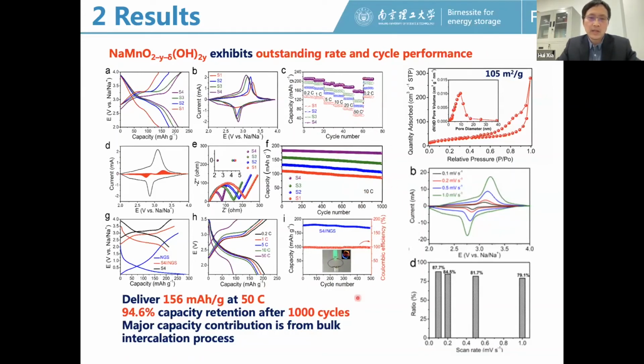Which indicates that this layered structure is highly stable, and it can have very fast sodium diffusion at the interlayer.